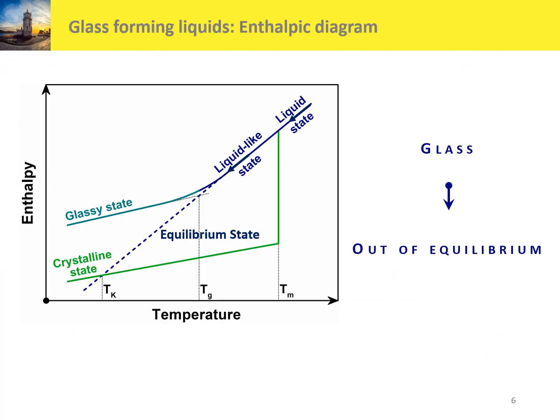To illustrate the glass forming ability, we can use this enthalpic diagram. When a liquid is cooled fast enough to avoid the crystallization, we reach the liquid-like state, and at a certain temperature called the glass transition temperature, noted Tg here, we form a glass. A glass is out of equilibrium, and the equilibrium state corresponds, in fact, to the dotted line here, which corresponds to the extrapolated curve of the liquid-like state.